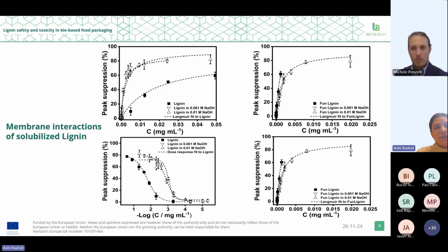So here in these calibration curves, I have compared the peak suppression, and hence the membrane interactions, caused by the lignin and functionalized lignin in the absence and presence of sodium hydroxide. We can see that the lignin interactions increased with an increase in concentration, both in the presence and in the absence of sodium hydroxide.